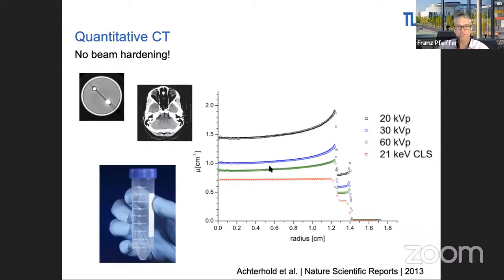And this is just some profiles highlighting this. This is a polychromatic spectrum with a typical cupping artifact at the center. If you take a simple cylinder of water, and this is the Munich compact light source, which gives you a quantitatively exact measurement of the attenuation coefficient, and it's flat over this container.